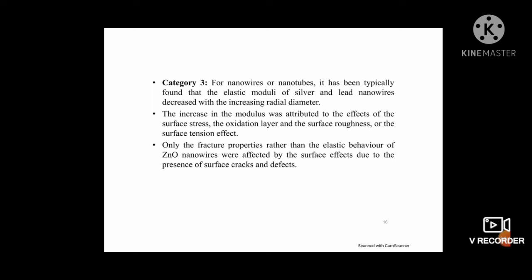The increase in the modulus was attributed to the effect of surface stress, the oxidation layer, and surface roughness or the surface tension effect on the fracture properties rather than the elastic behavior of zinc oxide. Nanowires are affected by the surface effect due to the presence of surface cracks and defects.